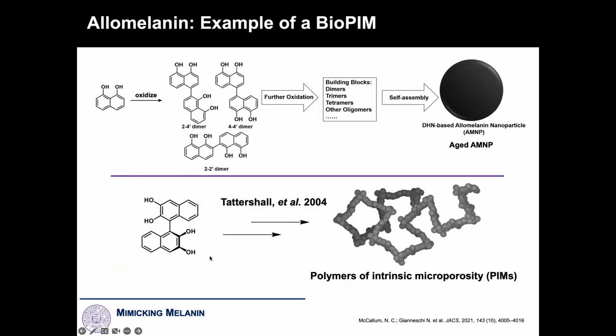If you look at some of the very first papers on polymers of intrinsic microporosity, so these are polymers that already are porous, this was one of the first ones they made. This is a group in the UK, published this in 2004. I wasn't really paying too much attention to that, but I probably should have, because you can see, right, the dimers we make, and obviously the oligomers that probably are being made by the organisms are actually quite similar to these species. Now, different in key ways, but as it turns out, as we've gone on and explored the natural melanin itself, it actually doesn't look dissimilar to the type of things that humans reinvented in the 21st century. So, right, these organisms have been doing this for billions of years.